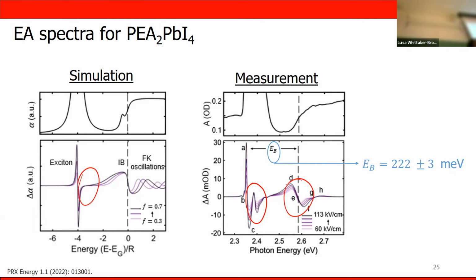So now that we know that, the difference between the excitonic peak and the band edge will give me the exciton binding energy, plus or minus 3 milli-electron volts, okay? So it's a very tight fit.